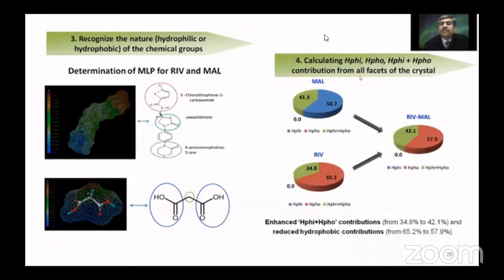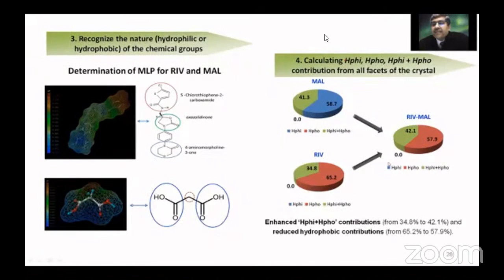Then we calculated the relative contribution of hydrophilic, hydrophobic, and the combination of both to the facets. And we came up with this interesting observation. In the case of malonic acid, this is the contribution from the hydrophilic groups, while for rivaroxaban, this is the contribution. So the majority of the contribution is coming from the hydrophobic groups. While there is nothing which is completely hydrophilic, this zone indicates the facets which have both hydrophilic as well as hydrophobic groups. While in the case of the co-crystal, we can see that the hydrophobic groups have reduced from 65.2 to 57.9, while the combination of hydrophilic and hydrophobic groups had increased from 34.8 to 42.1.